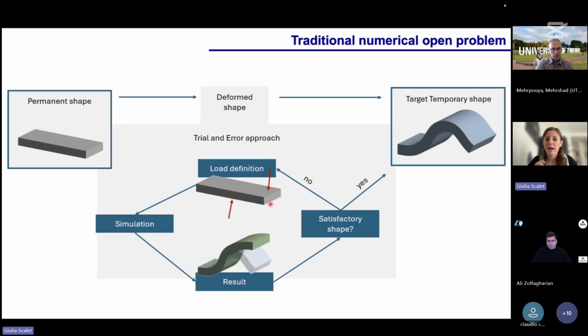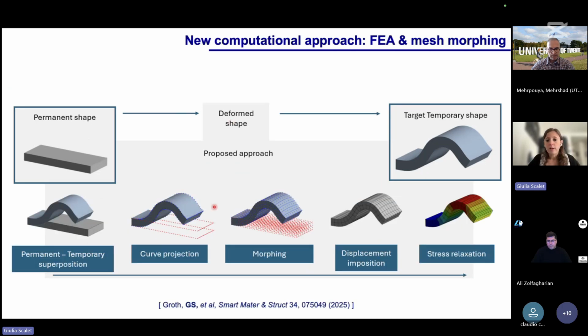So it is essentially a sort of trial and error approach also for this numerical simulation, because you start to apply a load, a boundary condition, a value, but at the end it could be not the right one, so you have to change a lot. And this is especially true for very complex structures. And this is why we try to support this step by coupling this finite element simulation, so with our constitutive model, with mesh morphing. So mesh morphing helps us in order to skip this trial and error approach and to achieve the target temporary shape that should be usually known based on imaging techniques, or also if you have a target application, you know your target shape, and you can apply this mesh morphing technique in order to avoid this trial and error approach based on finite elements.